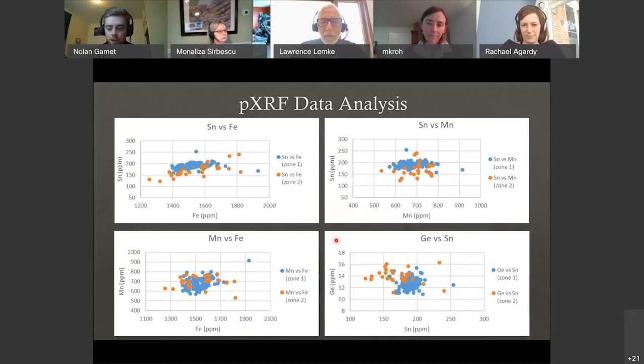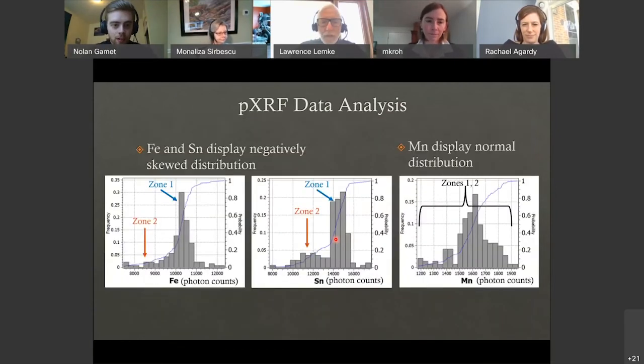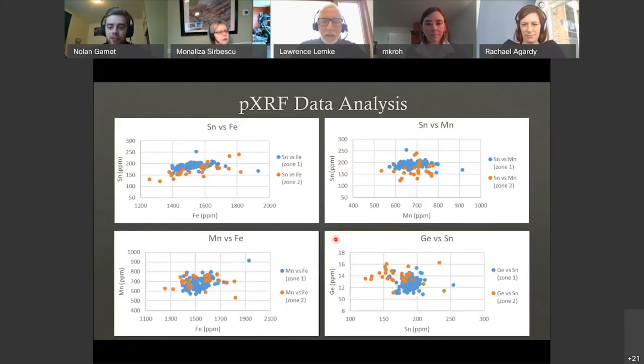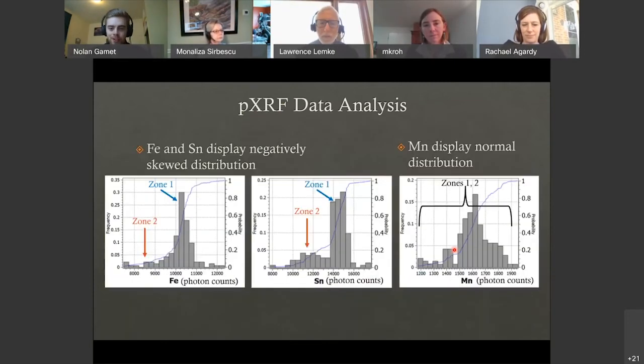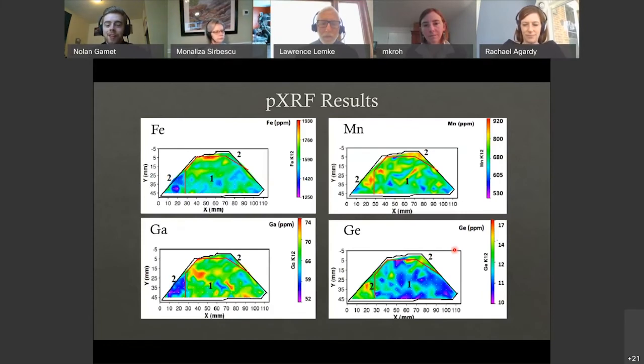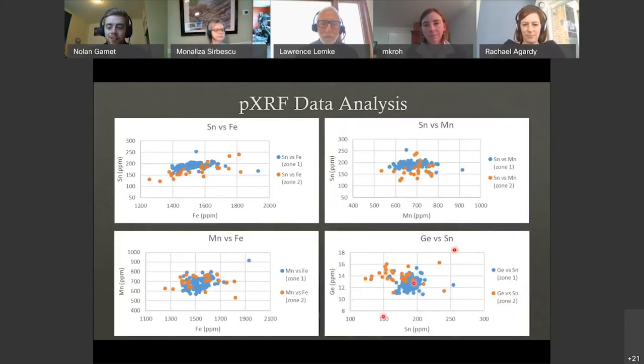Yes. One second. So yeah, germanium. Those are the cross plots right here. So germanium versus tin. So germanium was the incompatible one, right? And tin was compatible, and that can be seen here. So zone 2 had the high counts of germanium versus low counts in zone 1.